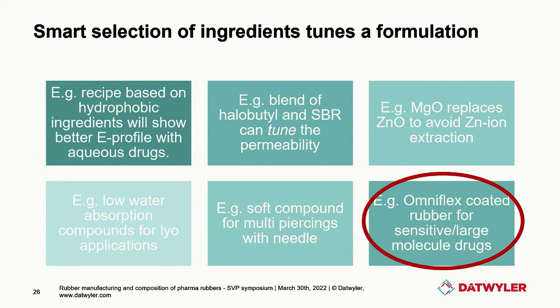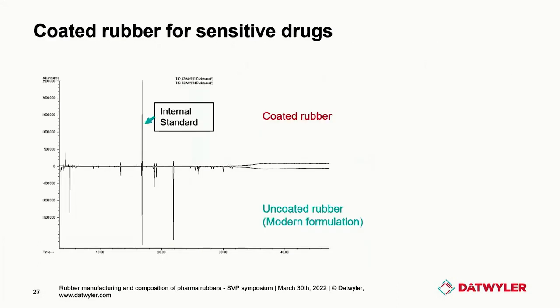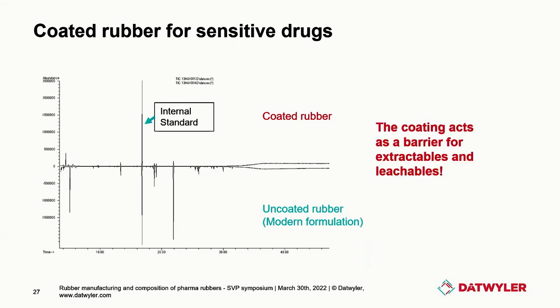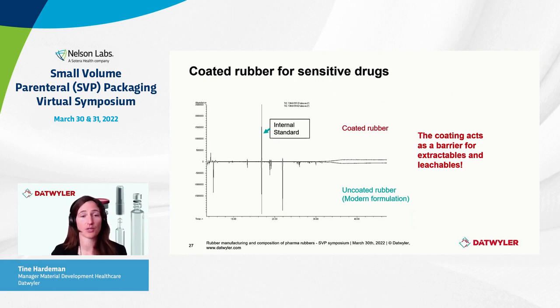Another thing that I wanted to mention is the Omniflex coating. So we have this Omniflex coating, which acts as a barrier towards extractables, because as I think many of you know, a coating will act as a barrier. So if you really need a very high purity, then you can add this coating to even further reduce extractables. So this is, for example, here below, you can see the chromatogram of an uncoated rubber, but already a modern formulation, because if you would look at older formulations, you would see really very crowded chromatograms, and the rubber industry has already evolved, in fact, greatly, and really reduced this amount of extractables. However, of course, you cannot go to zero extractables, so there will always be some, and in case you really need to reduce them further, a coating can help to either eliminate or reduce the amount of extractables that you are seeing. So for very sensitive drugs, of course, a coated rubber is also an option.